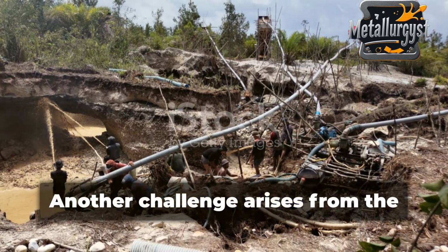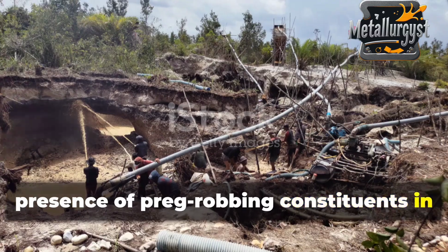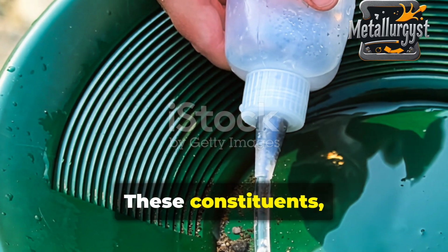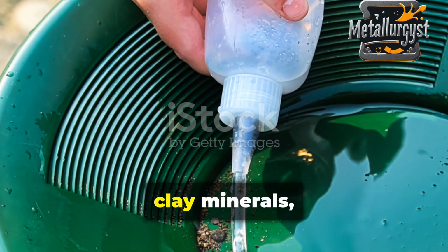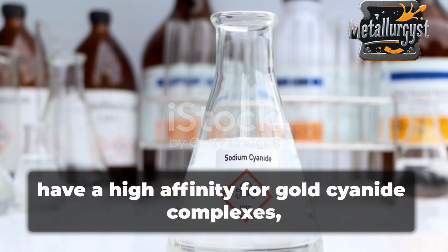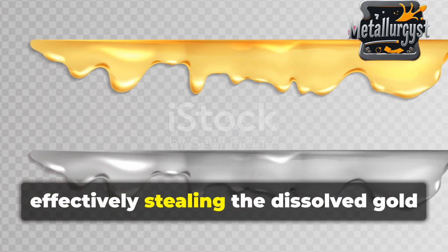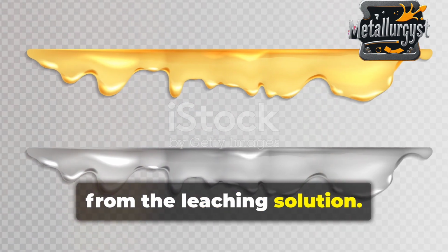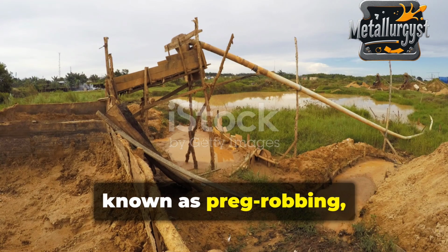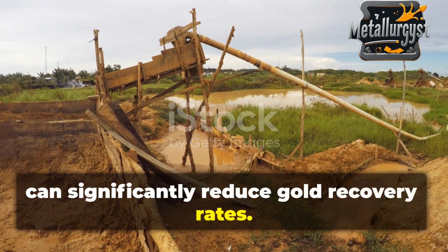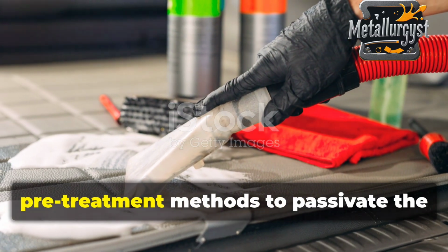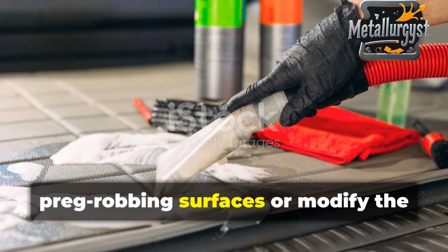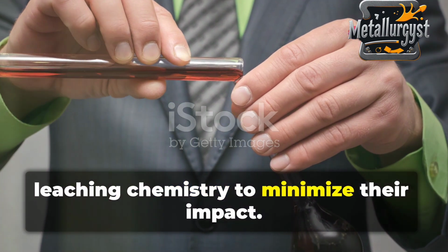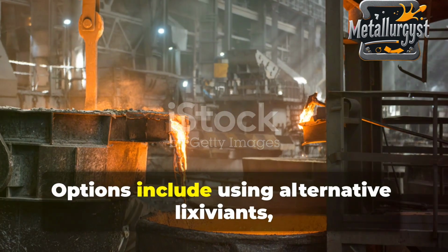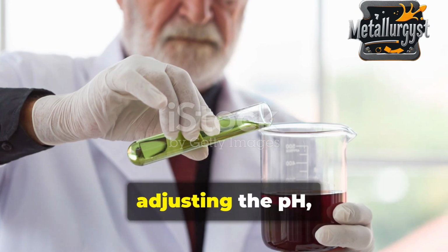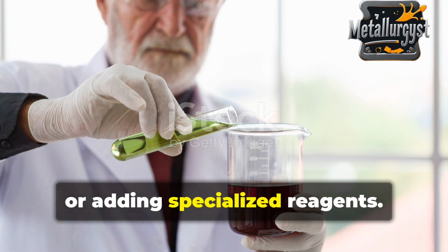Another challenge arises from the presence of preg-robbing constituents in the ore. These constituents, typically carbonaceous matter or certain clay minerals, have a high affinity for gold cyanide complexes, effectively stealing the dissolved gold from the leaching solution. This phenomenon, known as preg-robbing, can significantly reduce gold recovery rates. Mitigation strategies involve pre-treatment methods to passivate the preg-robbing surfaces or modify the leaching chemistry to minimize their impact. Options include using alternative lixiviants, adjusting the pH, or adding specialized reagents.